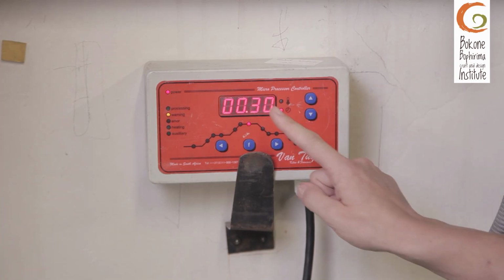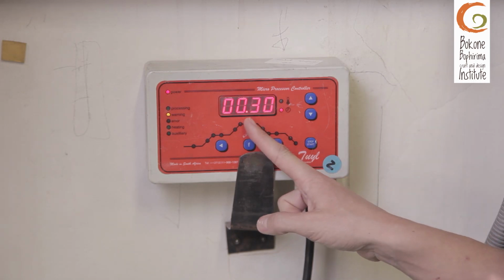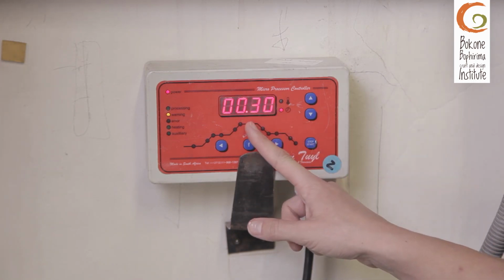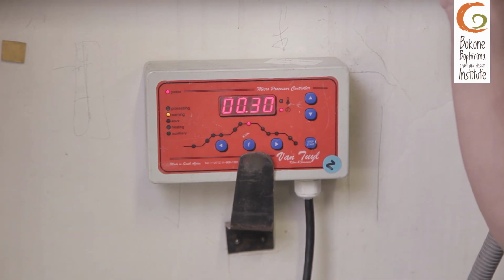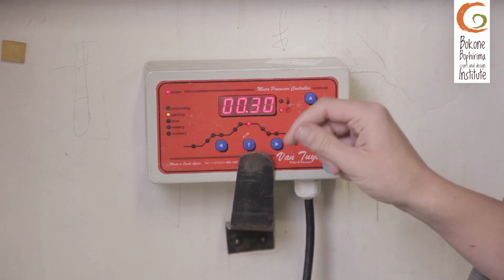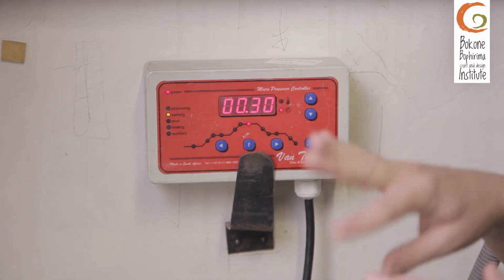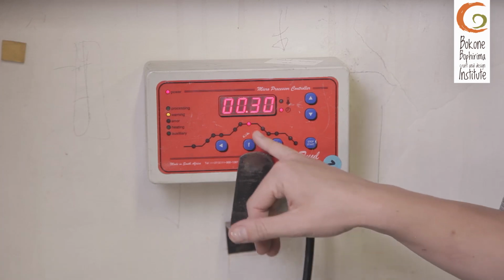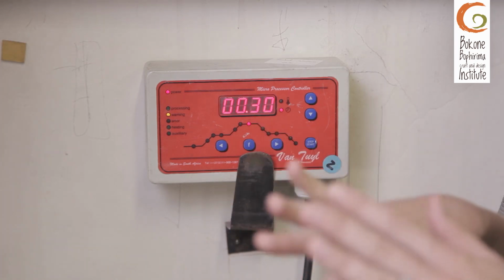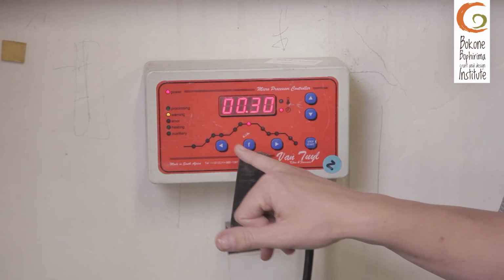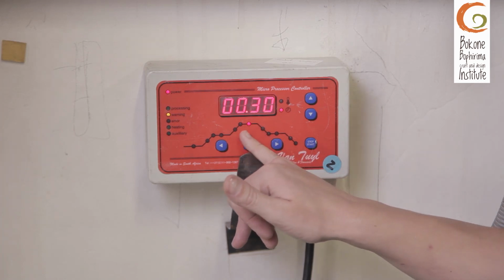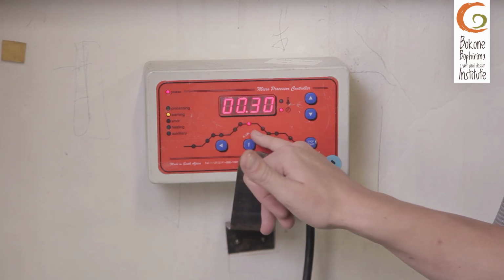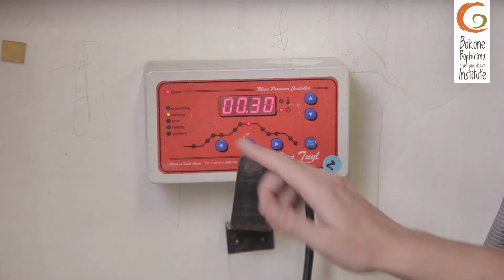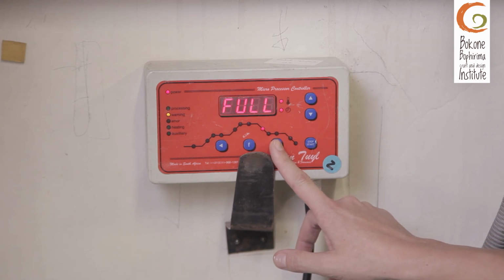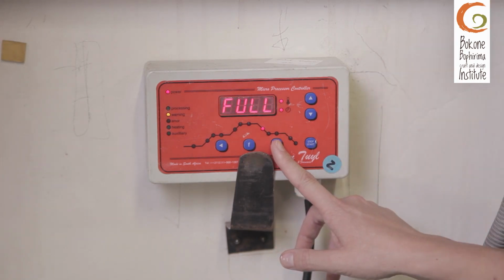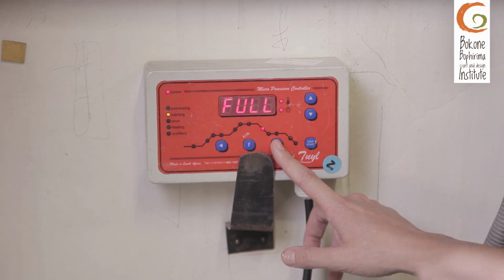One can also, in this process, especially with slumping, just before you hit your 30 minutes, peek open the lid of the kiln and double check that you are happy with your desired shape that you have. If you feel it has not completely slumped into the mold, rather quickly go back into your program and allow it to hold longer at that top temperature. We are then going to crash cool. So we want it to go as fast as possible down, because we are not manually doing this.